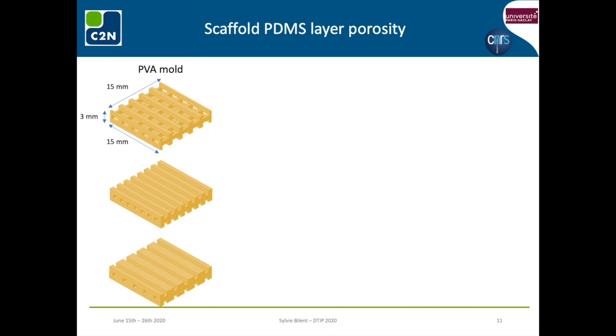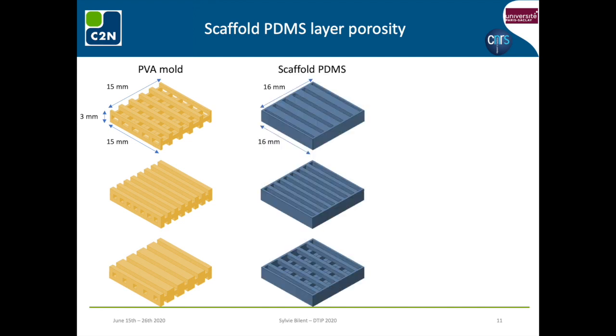You can see here some examples of 3 mm thick samples with various channel geometries, 1 mm high and 1 to 2 mm large channels, and 3D stacked arrangements. Yellow samples are PVA negative mold, and blue samples are resulting PDMS scaffolds. Other samples featuring the same kind of channel arrangements but with thicknesses of 4.5 mm and 6 mm were also fabricated.